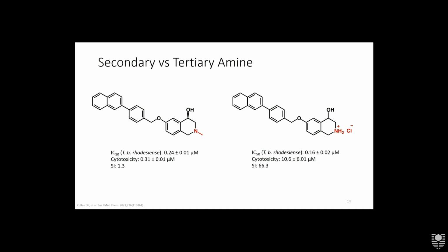In other cases, such as this one, this here was identified as one of the most promising tertiary amine derivatives, but that good potency against the parasite also led to quite a high toxicity. So converting that tertiary amine into a secondary amine, we maintain that good activity. It didn't really change too much, but we lower the toxicity significantly, meaning we have a much better selectivity index.